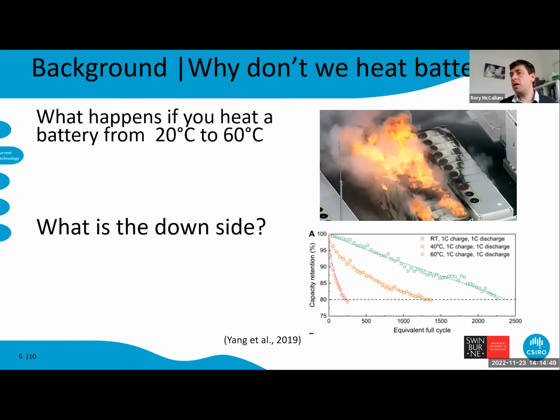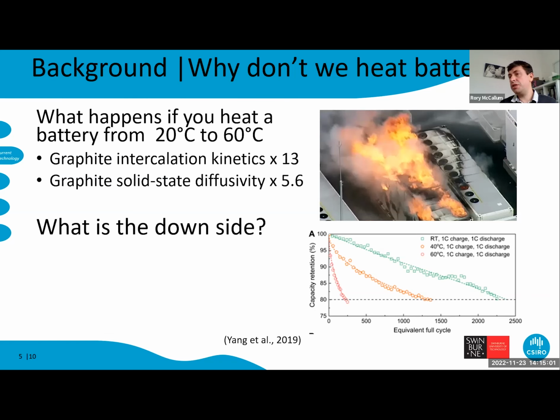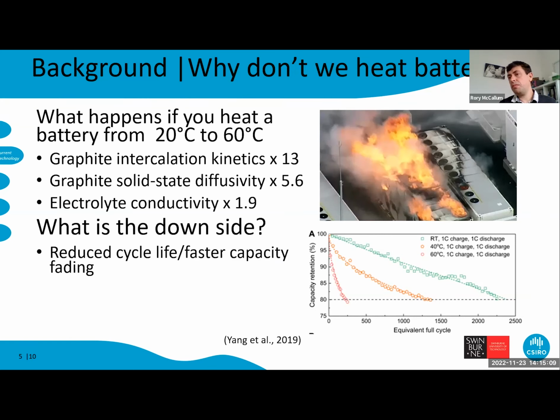But if we just look at what happens if we heat batteries up to 60 degrees, this is well below the limit of getting to these thermal runaways. We see increases in graphite intercalation and solid state diffusion. We also see electrolyte conductivity increase by almost double. And so this leads to a much faster charging and discharging cell.